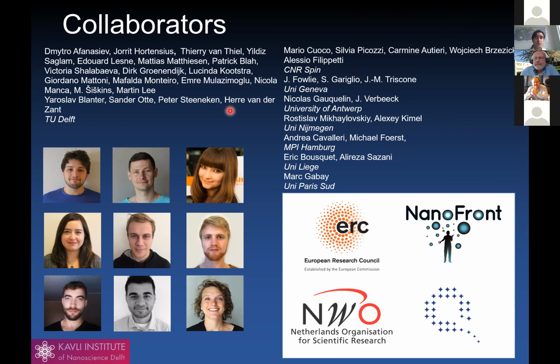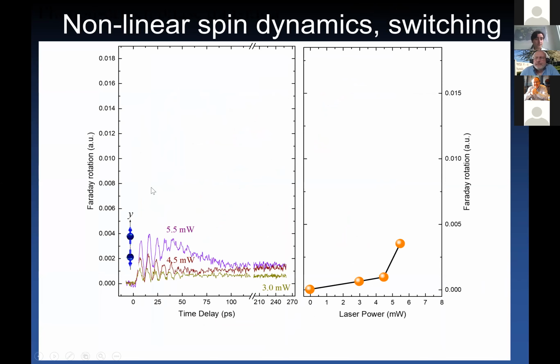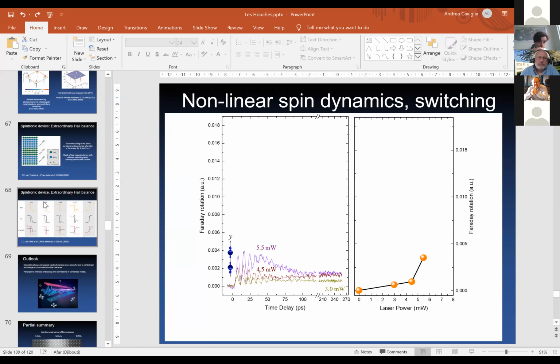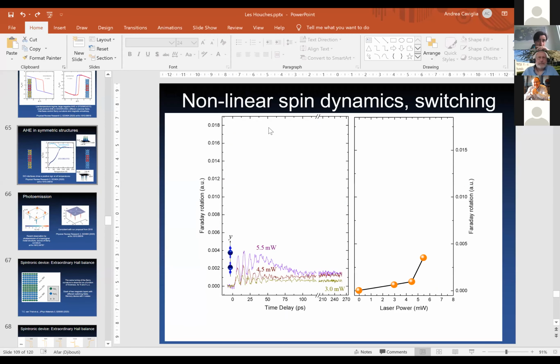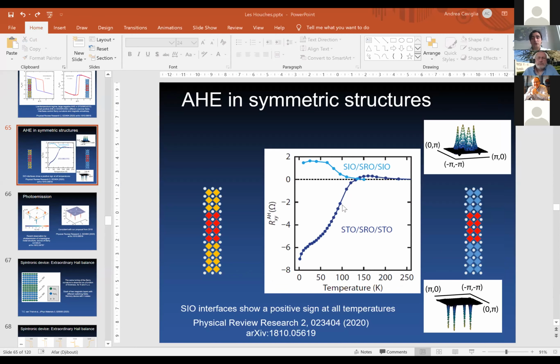Yes. So we had a question on the Berry phase aspects. Here I went a little bit fast, but essentially this transition from a positive to a negative sign of the Hall effect also depends on the thickness of the strontium ruthenate layer. So you can switch this transition to occur from higher temperature to lower temperatures. By doing so, you can create a temperature range in which one layer of strontium ruthenate has a negative sign of the anomalous Hall effect, and one layer of ruthenate has a positive sign of the anomalous Hall effect. And this realizes this extraordinary Hall balance configuration, in which you have four possible accessible states in your system.